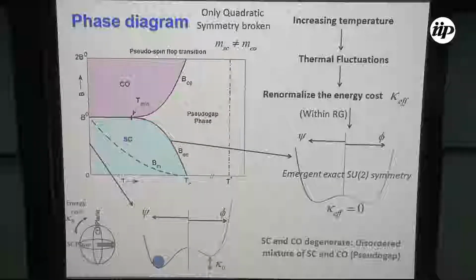line. So what happens is that if you increase the temperature further, there is no anisotropy. As a result, the system hesitates between charge order and the superconducting order, and the superconducting order or charge order at high field will go to a pseudogap phase, which will be a disordered mixture of charge order and superconducting order with no long-range coherence.